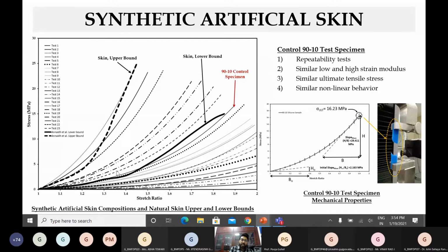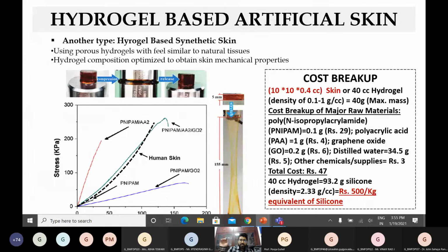So that is already complied because we are looking at a behavior which is very similar. So this is your 90-10 control specimen, which is very close to your skin lower bound with a very high amount of correlation index. So this is correlating fairly well. This is how we end up forming an artificial skin simulant, or an artificial skin development is taking place.